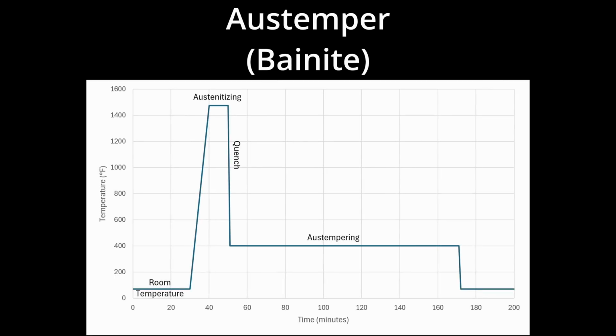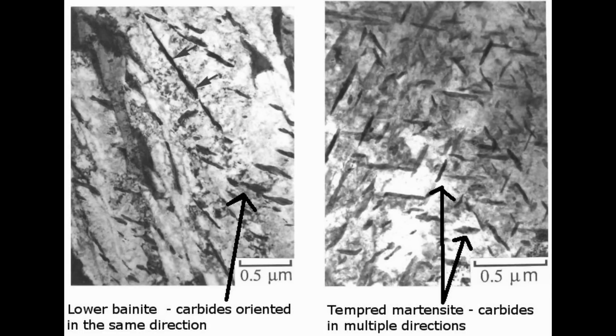An Austemper, instead of quenching to room temperature, we quench to an intermediate temperature, like 400, 500 degrees Fahrenheit, and we hold there until it transforms to a phase called Bainite. Bainite is similar to our normal quench and temper martensite. In fact, without electron microscopy, it can be extremely difficult to differentiate between tempered martensite and Bainite, but they can have different properties in some important ways.